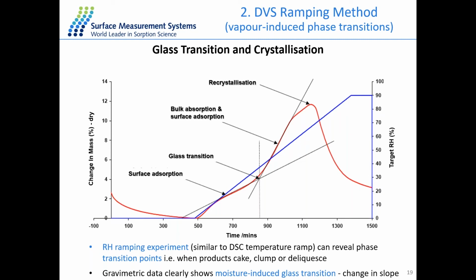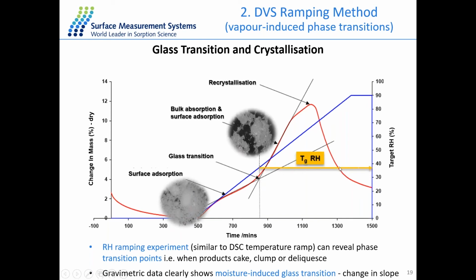And here's the result for the lactose sample. And it's quite clear that this lactose is first losing the mass because of the drying stage. And then the water sorption begins very slowly because of the surface sorption at the very beginning here. And after a certain point of humidity, the mass increase will become dramatically changing here because the water is not just on the surface, but also penetrates the surface and goes to the bulk of the material. So by comparing the slope before and after this change, we can get this point for the glass transition, and we can easily detect the glass transition humidity for this sample at 25 degrees.